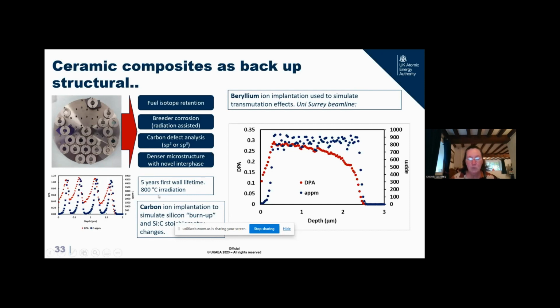And so we're emulating 5 years of first wall lifetime. We're having a look at how transmutation burns up the carbon part of the silicon carbide stoichiometry, so how the material is actually changing in terms of composition, what defects are arising, and actually if we put this alongside a liquid breeder, would the corrosion from the liquid breeder lithium cause damage as well? We know it does with the steels. We are also evaluating now with the ceramic composites.